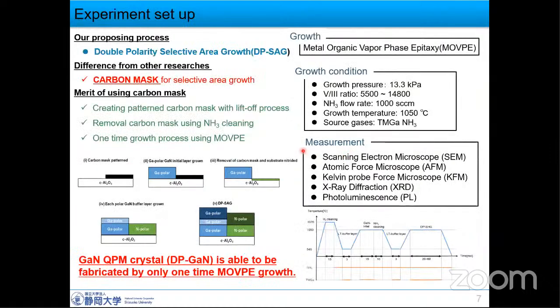So our proposed process is called double polarity selective area growth, DP-SAG. DP-SAG has the feature of using a carbon mask, and the merit of using a carbon mask is creating the pattern with a lift-off process. The carbon mask is removed using ammonia cleaning, and it needs just one growth process.